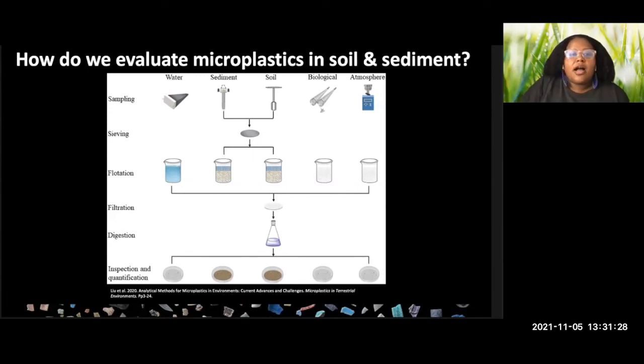And a density separation can take between 24 to 48 hours. Typically what follows after that is doing a filtration of whatever floats to the top. One big issue, however, is that if you don't get microplastics in your initial density separation, a lot of it is somewhat occluded in this solid matrix that is highly rich in organic matter. So a digestion step is typically employed, such as Fenton's reagent, which is the most cost-effective approach that's been used, or enzymatic digestion, which is incredibly expensive. So those are the two methods that are primarily used.